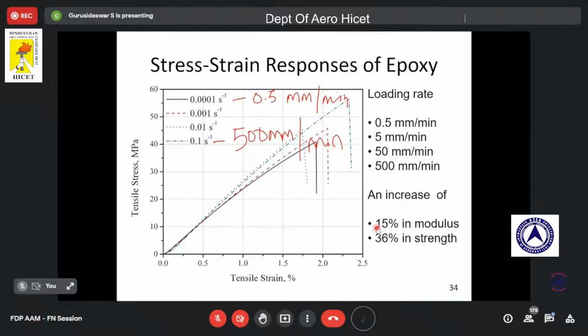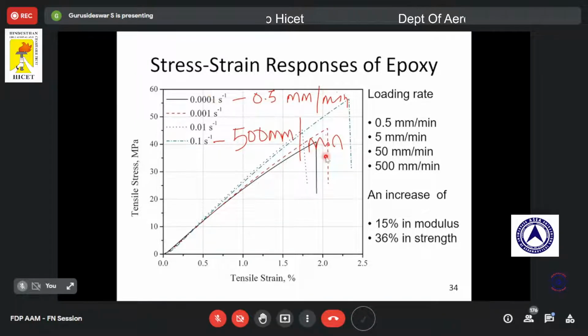So we have found around 15% increase in the tensile modulus from low to high strain rate. Again, we have found around 36% increase in the tensile strength. You can observe here, at the lowest strain rate, 0.0001 per second, we have got around 40 megapascal, wherein at the strain rate of 0.1 per second, that is 500 mm per minute, we can see a strength of 55 megapascal. This is the behavior of the material. So from this we can see the epoxy is rate sensitive.